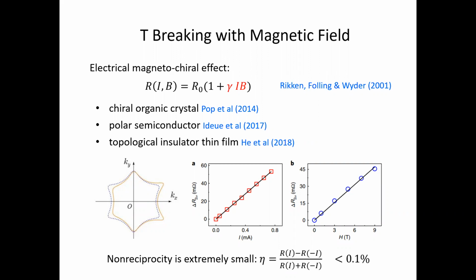And this effect has been observed experimentally in a few materials, including the recent experiment on topological insulator thin films. Here I'm showing you the results. Because this correction is small, you can single out the correction to Ohm's law using an AC input current and measure the resistance at the frequency 2 omega, because of this frequency conversion that I just mentioned. And indeed you see that there's a non-reciprocal resistance that depends linearly on the current. It also depends linearly on the applied magnetic field, so it's only present when the magnetic field is applied, okay?